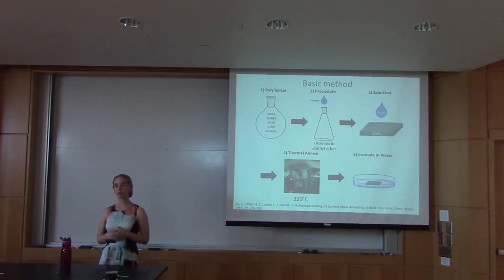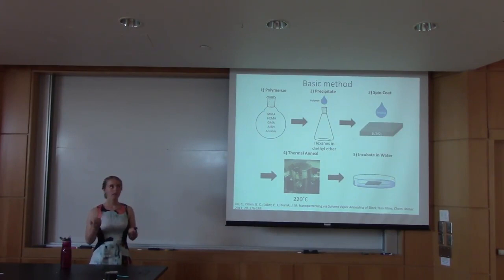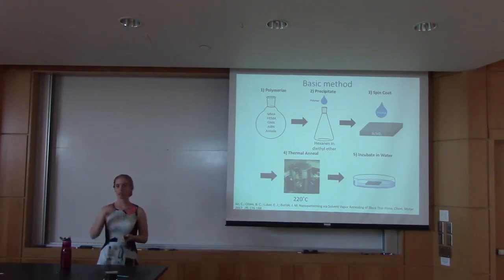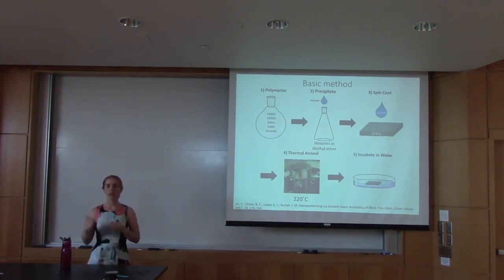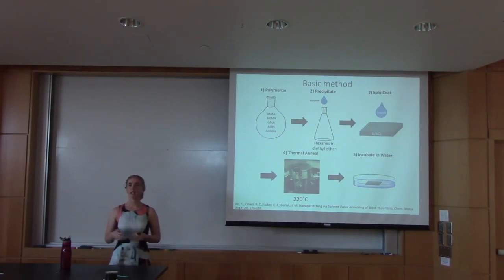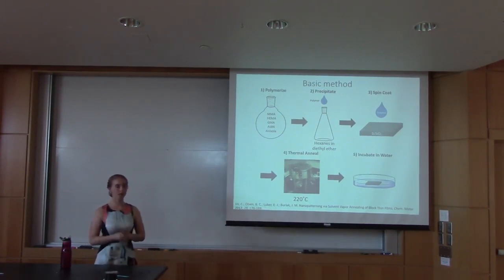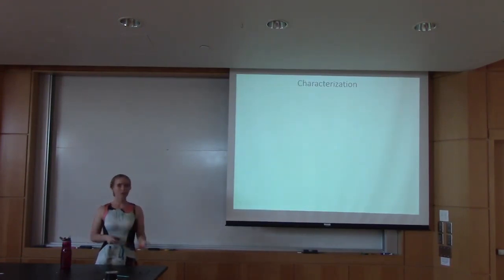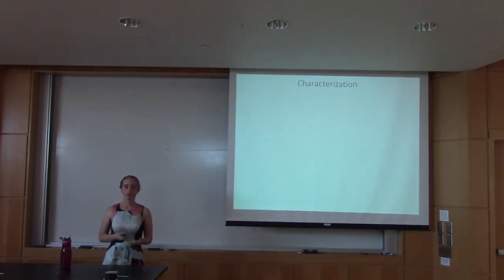It's actually really important because it allows us to have a more uniform surface. So if you recall, the HEMA part of this random copolymer is more hydrophilic, and so they'll orient the more hydrophilic parts closer to the surface, and it'll allow for just more uniformity in the orientation of this block copolymer. Sorry, in the random copolymer. So after we've done all of that, we need to characterize it.